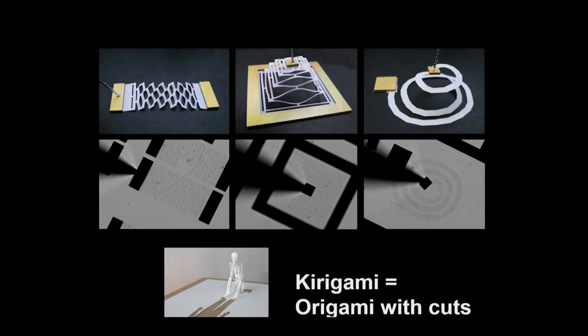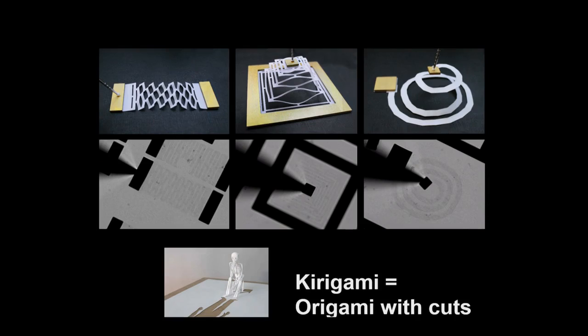And in fact, you can make very simple things. Some paper models are shown here, and then realize them in their graphene versions down here. And that's what's shown here. By the way, these paper models are not just for visualization's sake. As I told you, everything is scale invariant in this kind of approach. So if you get the ratio of the length to the thickness of the paper right, it'll act about the same way as these models. And it turns out for the size of these things that we're making in graphene, about 10 microns or 20 microns long, the effective length to width ratio is comparable to a standard sheet of paper. So we play with the paper models, and that actually informs what's going to happen in the actual microscale system. So that's kind of fun.